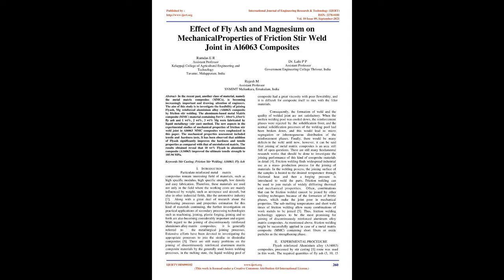The aluminum-based metal matrix composite, MMC, material containing 5 Wt%, 10 Wt%, 15 Wt% fly ash and 1 Wt%, 2 Wt%, 3 Wt% Mg were fabricated by liquid metallurgy, stir cast, method. The new aspects in the experimental studies of mechanical properties of friction stir weld joint in Al6063 MMC composites were emphasized in this paper. The mechanical properties assessment included tensile and hardness tests.